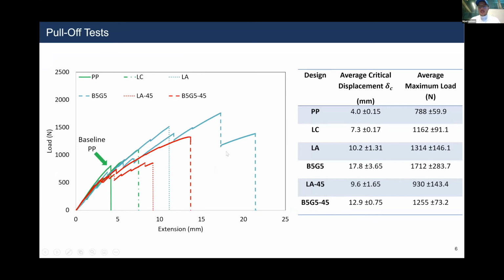So the mechanical results of the pull-off test showed how when we had the baseline peel-ply treated T-joints, catastrophic failure happened, while as we employed the laser pretreatment, the toughness increased. And the best toughness was achieved using the patterning, the B5G5, with a 0-degree ply orientation on the surface. This actually resulted in improving the critical displacement by 4 times and improving the area under the curve, which is the energy dissipation, by 12 times.